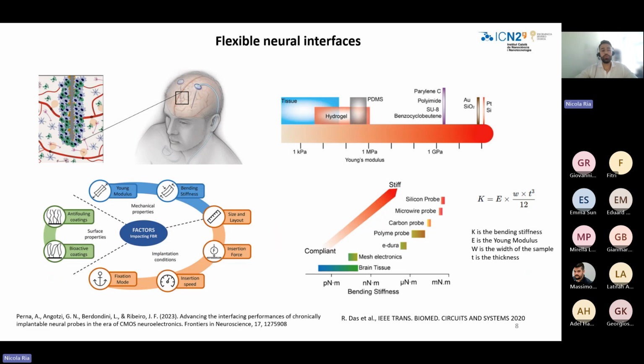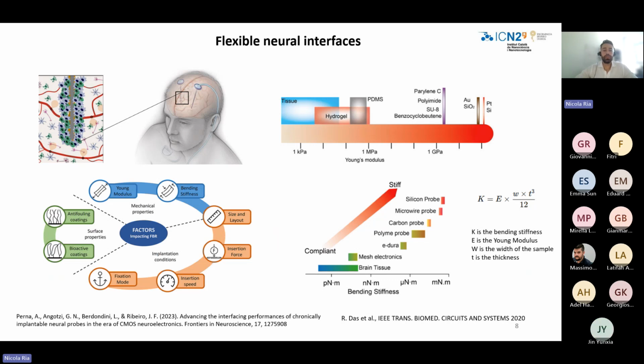So the importance of having a flexible substrate is due to the fact that rigid implants over time have some problems, like after a few weeks or 1 month there is the formation of a glial scar around the device, which reduces a lot the quality of the recording and also the capability to inject current, so to deliver the therapy. This is due to the mismatch between the Young's modulus of this rigid device and the brain. And also it is due to other factors like the size of the device, the insertion force, or the insertion speed. New materials are nowadays used as a flexible and soft substrate for electrodes like hydrogel, PDMS, or Parylene C, polyimide, SU-8.